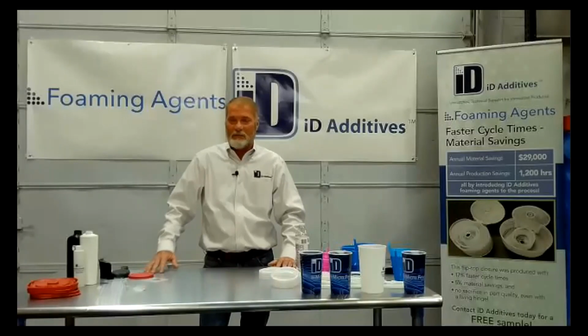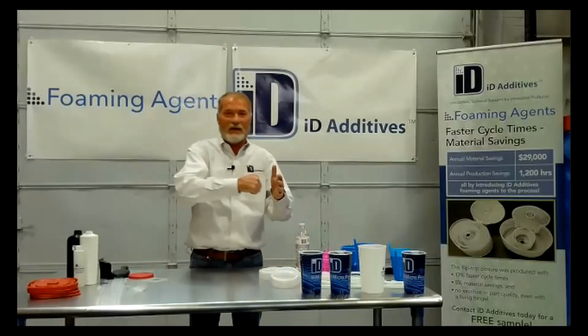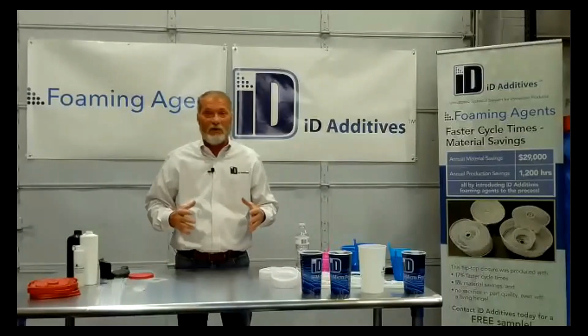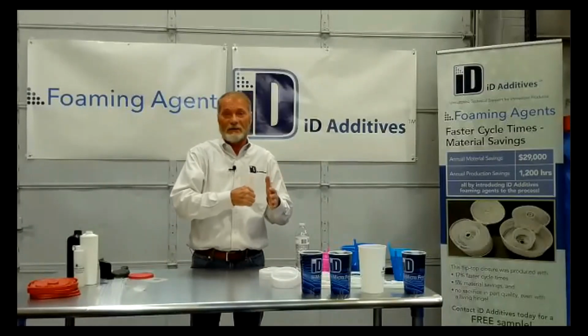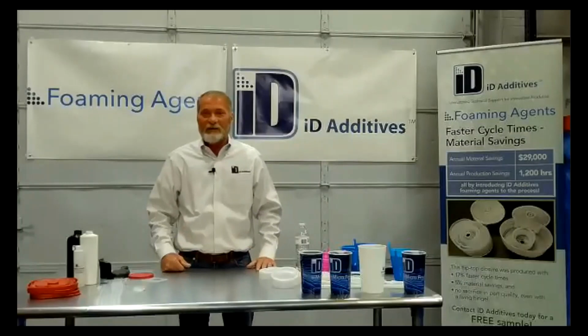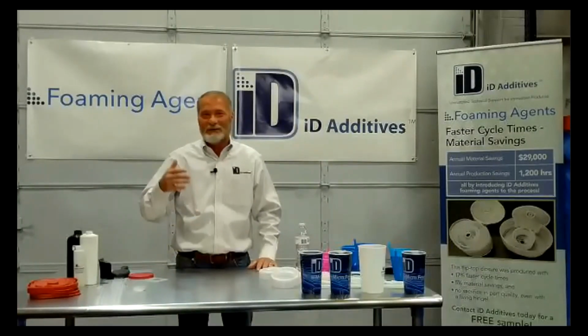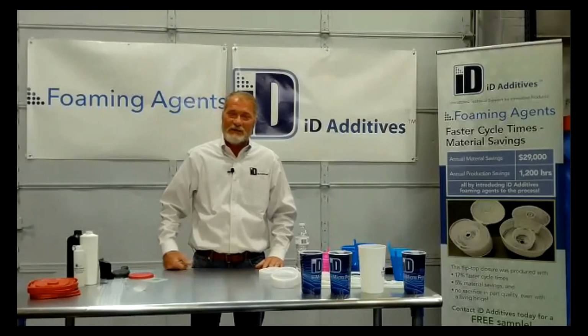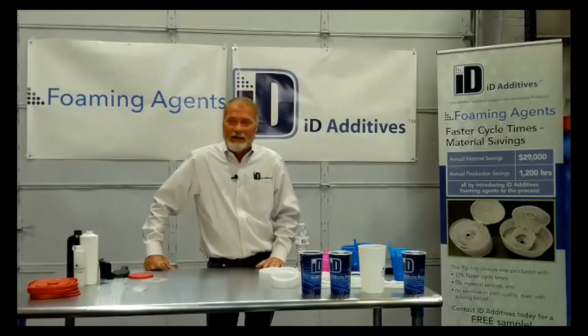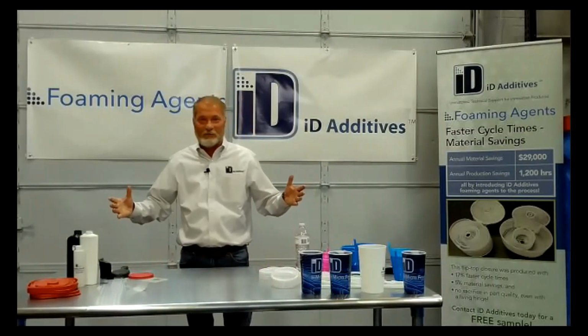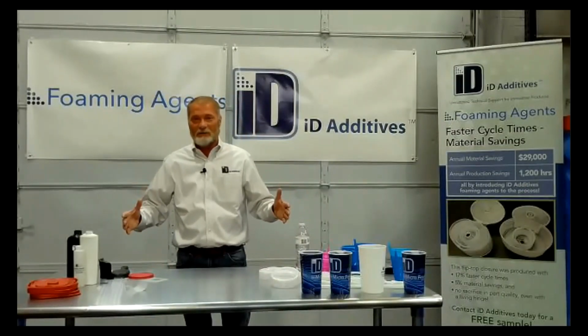So if you want to foam, vent that mold as much as you can, because you're actually going to go in quicker than you normally mold. I mean, anybody can just squeeze and squirt, push it in, fill it out, that's fine. But when you want to add foam, you want to get it in really quick. And better vents help if you're injecting faster. Typically when you're burning, that means your vents are bad. And then you have to slow your velocity down, and all of a sudden the burn goes away. Well, the reason for that is it's not venting well.